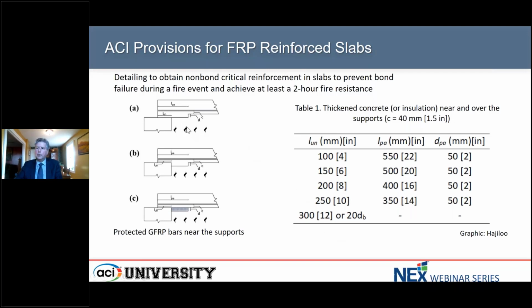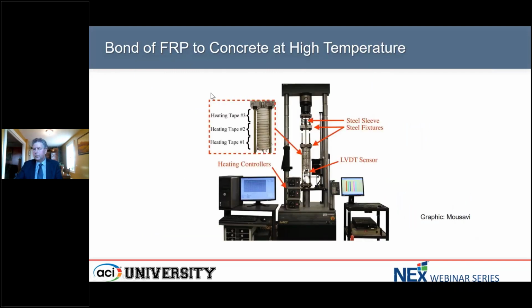But if you don't have enough room for that embedment, some options we've suggested is you could thicken the slab near the supports in either of these two ways, or you could provide some externally applied insulation. That could be a spray applied insulation, or could use gypsum boards, etc., to achieve that, to protect those end anchorages. So a little bit more on the bond of the FRP to concrete at high temperature.